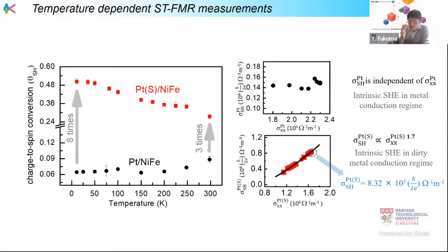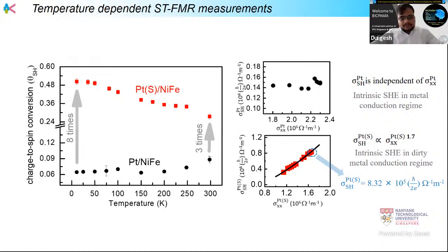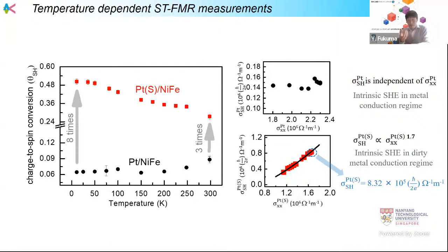We can say there are two different mechanisms of the spin Hall effect, like the anomalous Hall effect: intrinsic origin or extrinsic origin. Extrinsic origin is mainly scattering by impurities or some scattering factor. For the Hall effect, we need to bend the electron like this, so the scattering factor is very important. In this sense, when we increase the resistivity, we can enhance this kind of scattering, so the spin Hall effect should be enhanced. But in the case of sulfur-implanted platinum, with increasing conductivity, this kind of scattering also enhances. Maybe this could be related to some intrinsic properties of the material. Okay, thank you.